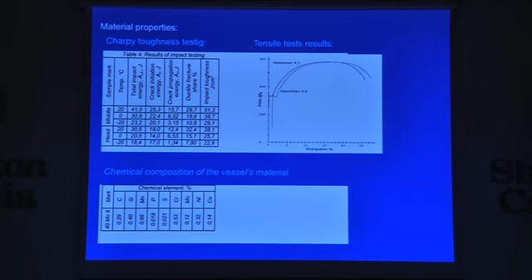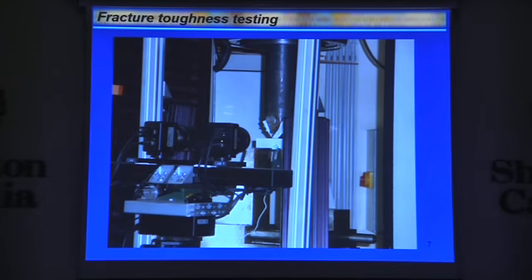So here you can see the results of fracture toughness testing at different temperatures and from different areas. Also here are the standard tensile test results, and the chemical composition of this material, which was determined from the samples. For the fracture toughness testing, we used 3-point bend specimens, observed the surface, and put the clip gauge according to ASTM E1820 standards.